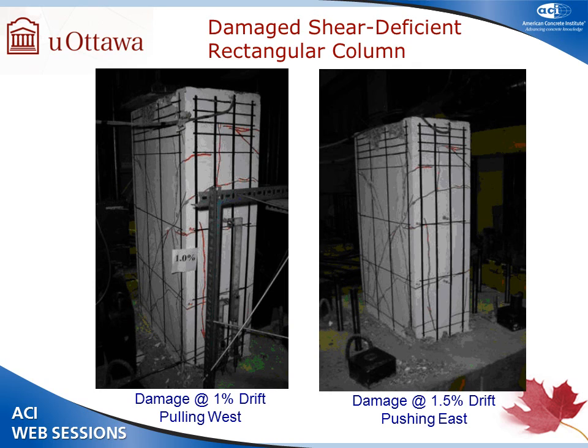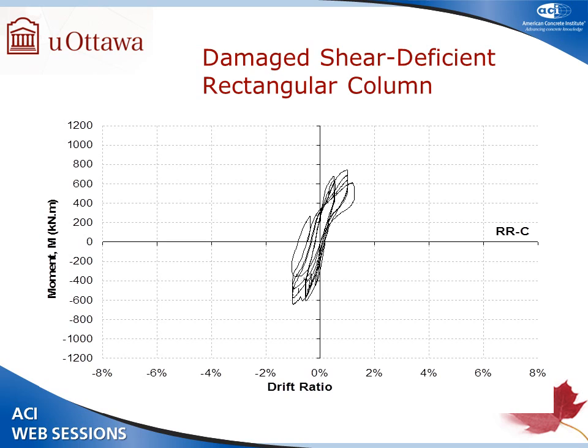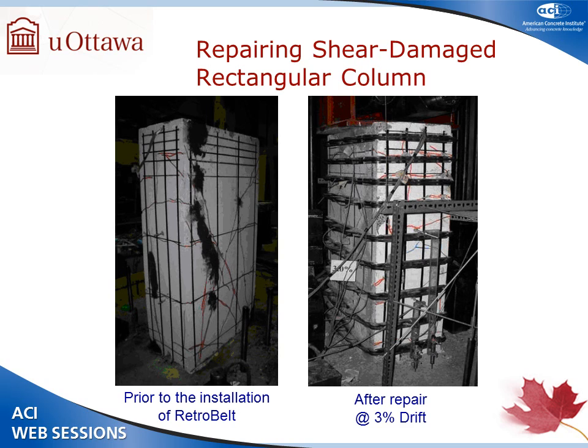So this is a rectangular column, and we were able to damage it at 1% drift in one direction and 1.5% drift in the other direction. And when we did that, it was damaged more in one direction. In fact, there was a somewhat strength decay, as you can see in the upper right quadrant. When we went to 1.5%, there was 20-25% strength decay, but in the other direction, we did cycle 3 times at 1% and then stopped. And then we simply patched up with grout and then started putting the retro belts and applied 50% of prestressing at H/4 spacing.